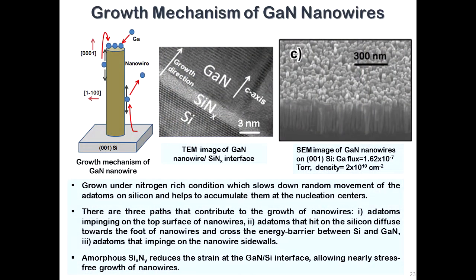So let me start with the two nanostructures that I was going to talk about. Now, I will admit that I used to go to conferences and laugh at nanowires. Simply because some of the earlier work, not with nitride nanowires, but with the arsenide nanowires, I knew were not device worthy, and one couldn't even do good material science with those. But then the gallium nitride nanowires came, and these were a totally different beast. So we grow them on silicon.